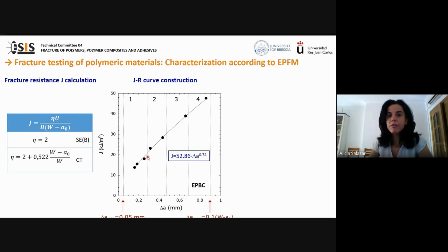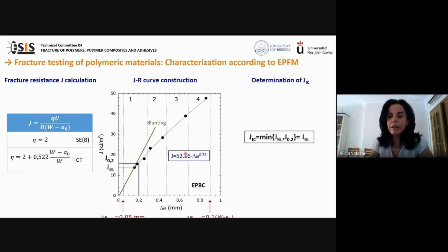The resistance curve is fit to a power law, shown in blue. Finally, for the determination of the J1C, the energy at crack growth initiation, we compute the minimum value of J blunting in green, obtained as the intersection of the blunting line with the JR curve, this point, and J 0.2, that is the J integral at a stable crack growth of 0.2 millimeters. In this case, J1C is equal to J blunting.